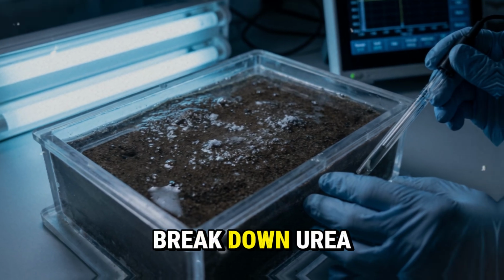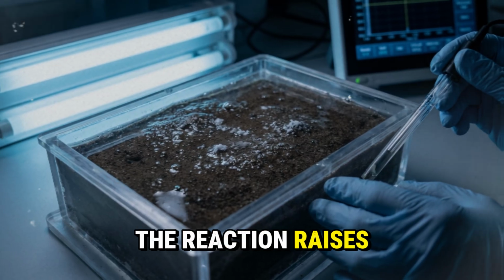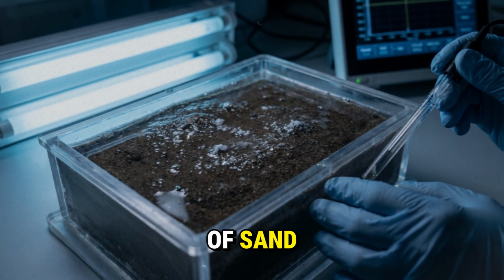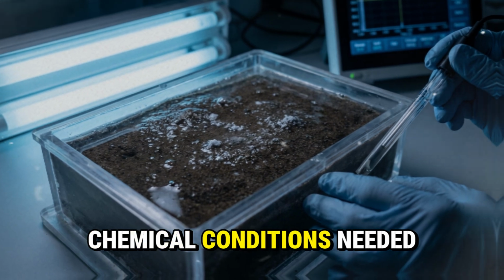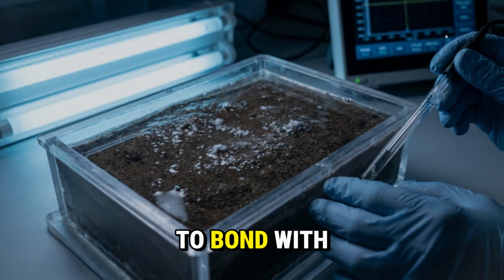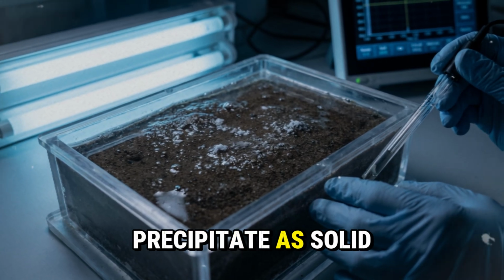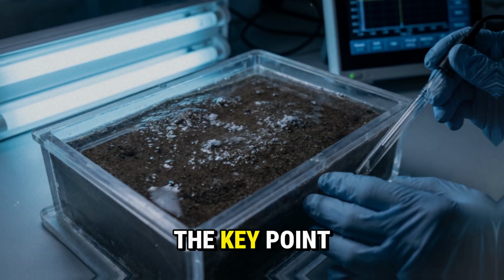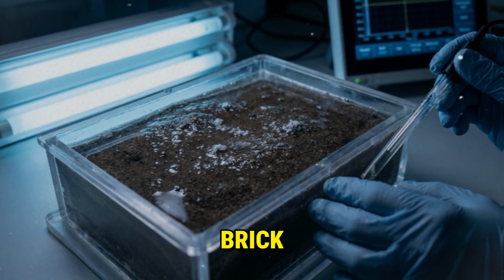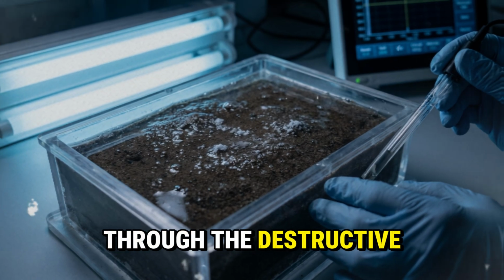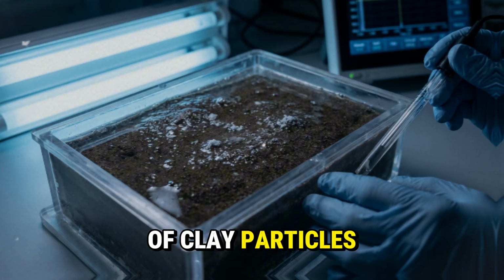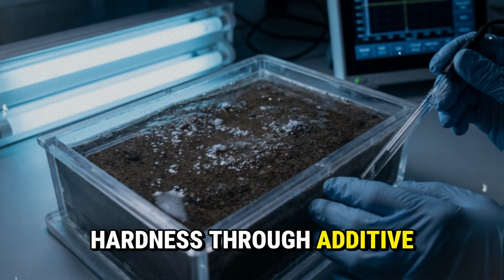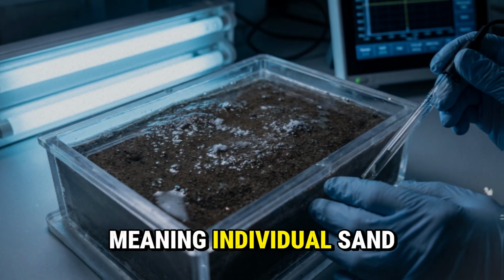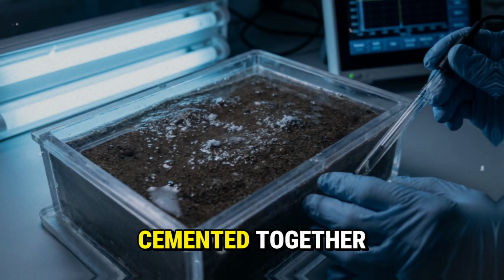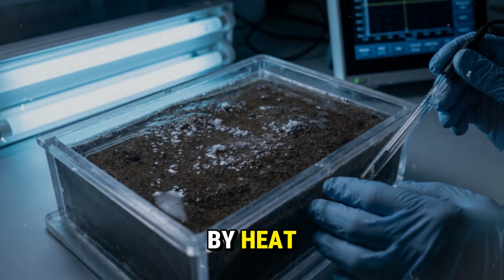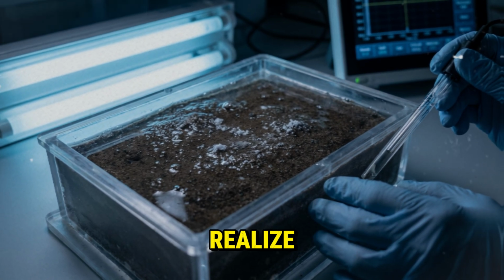As the bacteria break down urea in the solution, the reaction raises the local pH around each grain of sand, creating the exact chemical conditions needed for dissolved calcium to bond with carbonate ions and precipitate as solid calcite crystal. The key point here is that unlike a fired brick, which achieves hardness through the destructive melting and fusing of clay particles, this brick achieves hardness through additive mineral growth, meaning individual sand grains are being cemented together rather than transformed by heat. But here's what most people don't realize.